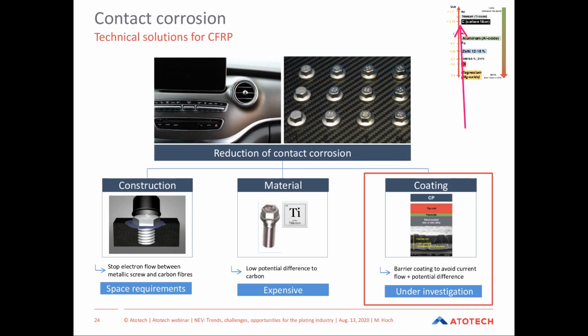Another possibility is a so-called CP combination, a combination of galvanic zinc or zinc nickel plus a passivate, and additionally protected by a thick top coat as a kind of isolation layer. Some examples of our investigations are shown in the next slides.